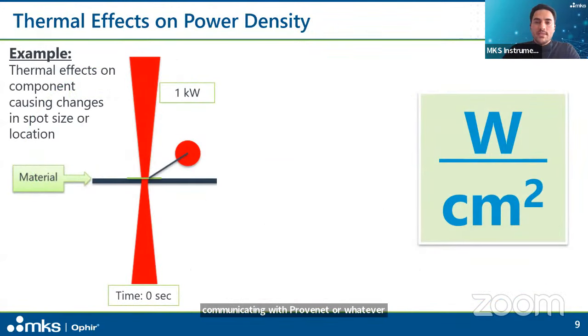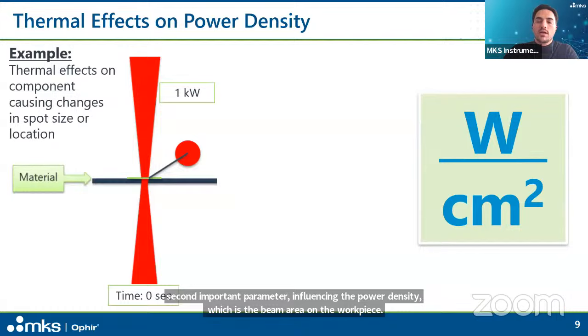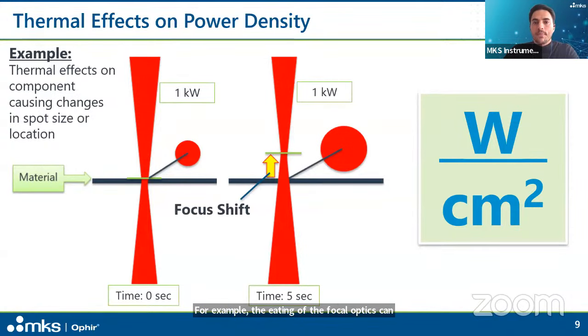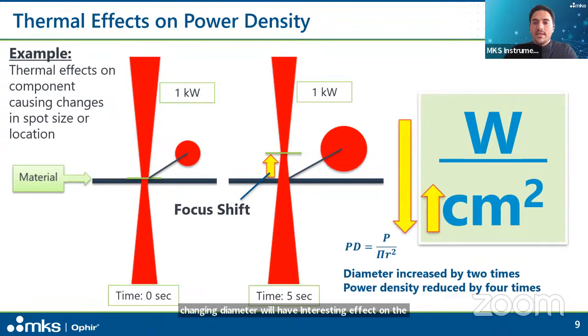The power variation was the easy part, so to say. Now let's move on to the second important parameter influencing the power density, which is the beam area on the workpiece. Here it gets complex. The variation can be very dynamic over time. For example, the heating of the focal optics can cause thermal lensing. This is quite common. If the focal position moves in the Z direction, the changing diameter will have a drastic effect on the area. And when the diameter is increasing by a factor of 2, the power density is automatically reduced by a factor of 4 because of the square in the formula. So to measure this parameter, we use what is called beam diagnostic or beam profiling.